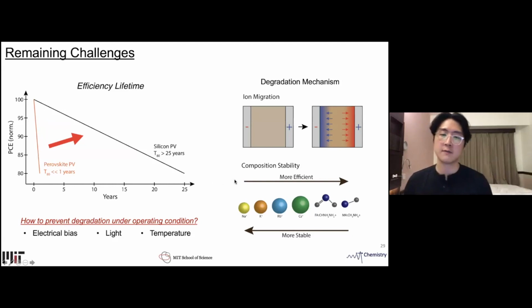Currently the trade-off involves a concept called the Goldschmidt tolerance, which determines what cations can form these perovskite crystal structures. Let me just move this. The cations shown here, Fa and Ma, fit nicely within that tolerance range. However, if we go toward these smaller alkaline metals, they start to fall out of that tolerance range, meaning you won't be able to make a stable perovskite crystal that results in high efficiency.